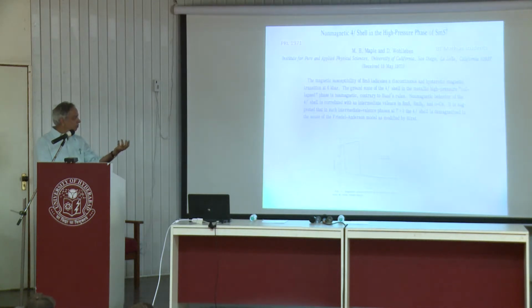Analyzing various data, they gave a time scale of the order of 10 to the minus 12, minus 13 seconds. Therefore, it was concluded that there is spontaneous fluctuation of the 4f electron between the 4f shell and the conduction band. The net result is that it cannot be magnetic, because there is no stability of the 4f electron in a particular shell. It does not know what it should do when it is fluctuating.